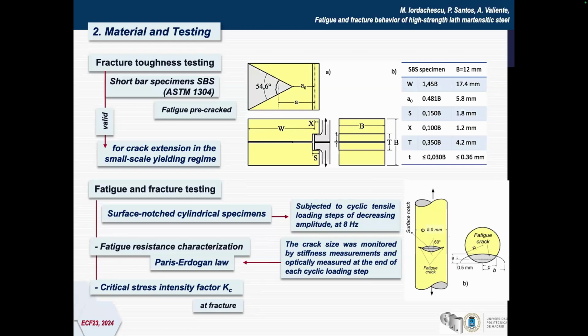These were subjected to distinct cyclic tensile loading steps at 8 Hz, and then the crack size was monitored by stiffness measurements and, of course, optical measurements at the end of each loading step for fatigue characterization and also for determining the critical stress intensity factor Kc at specimen fracture.